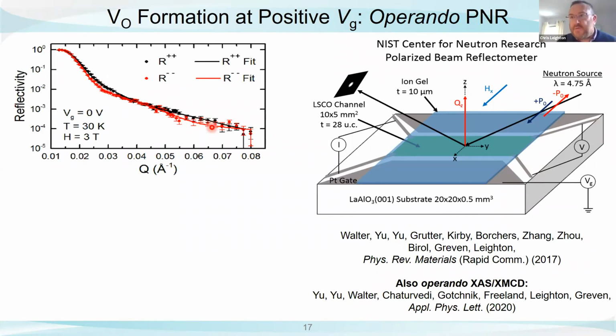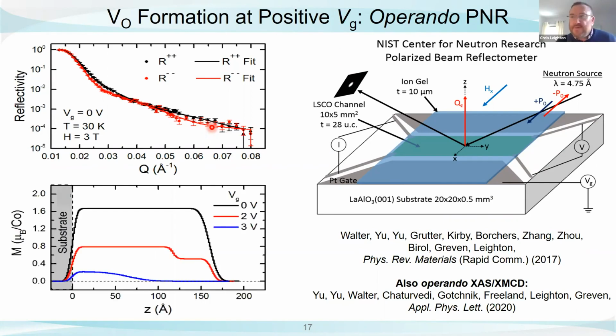And that's caused by the fact that we have a ferromagnetic film, right? So what's encoded in here is the Fourier transform of the depth profile of the magnetization. So we can pull out the magnetization by refinement as a function of depth. So here's our substrate. This is our oxide film. This is at 0 volts, then 2 volts, and then 3 volts. And our electrolyte is on the top of the film out here.